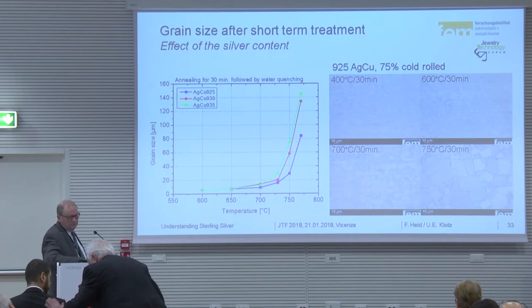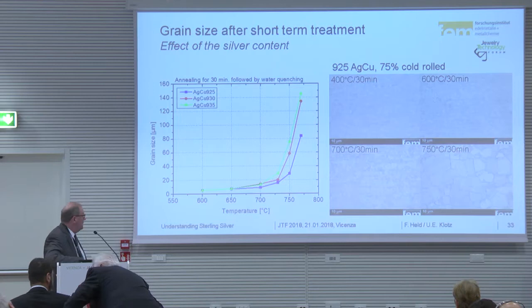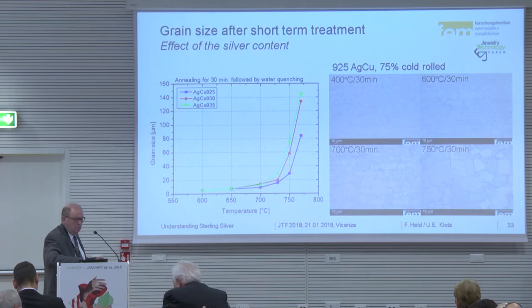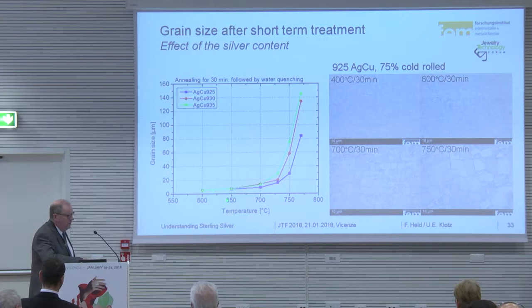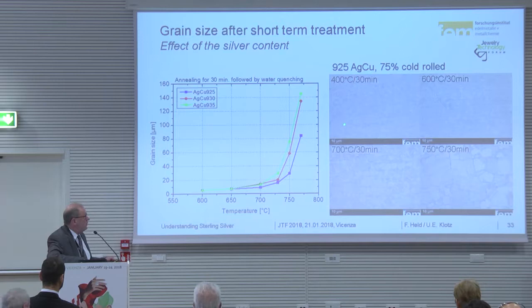This is grain size after short term treatment, effect of the silver content. So we say, okay, we have used these three alloys because these are used with the goldsmiths. We have here temperature, we have here the grain size, and you see that with 700 degrees annealing, no big difference. The difference comes if we come up to 750 degrees or higher.